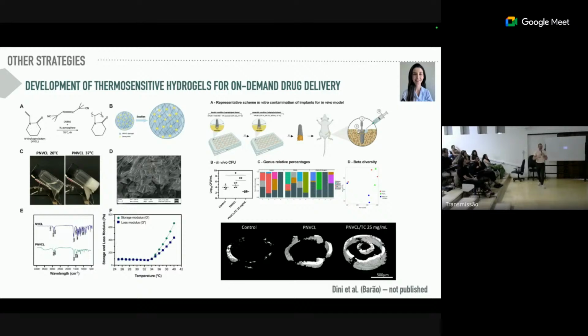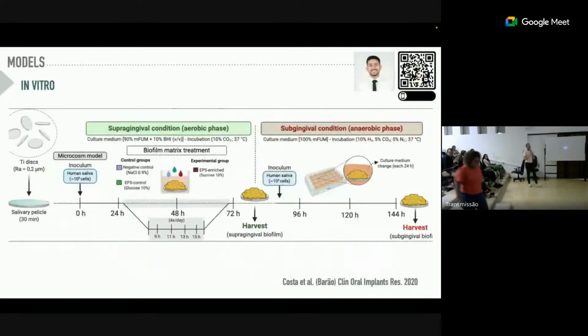using this tetracycline. We use an infection model, and we also have some in vitro analysis, but in vivo we show that the bone formation in the group treated with tetracycline and this hydrogel was better. We also have some data in terms of microbial composition. We also observe a better, healthier status when you compare to the non-tetracycline group.